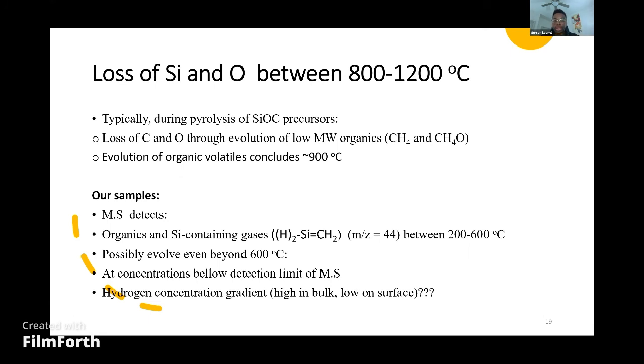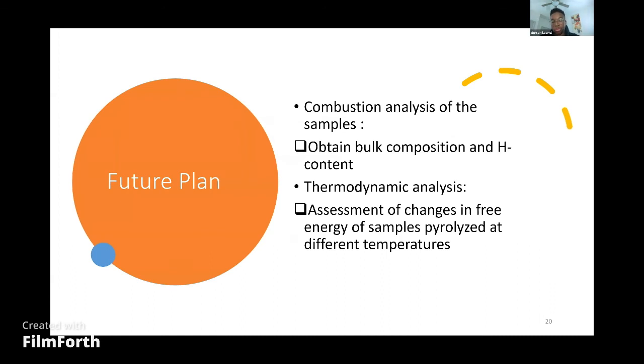Now, in order to confirm the presence or absence of hydrogen in the bulk of these materials, we would need to run further characterizations such as combustion analysis. And that is why, for our future plan, we plan on characterizing the bulk of these materials. And then after we have their bulk compositions, we'll be able to utilize high temperature calorimetry to perform thermodynamic analysis on the samples and observe how their thermodynamic stability changes as their structure evolves between 800 degrees centigrade and 1200 degrees C. From this work, we're able to determine how minor changes in the carbonaceous pendant groups in the oligomers actually result in significant changes in pyrolysis behavior, as well as in the structural evolution of their respective silicon oxycarbides. Thank you very much, and this is my presentation to you.